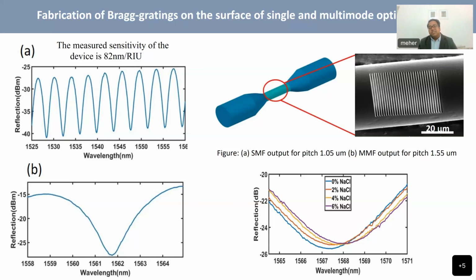These are really very challenging, and it took around a few months to optimize the process. Finally we could get it without coating any material. What people generally do, if they want to make surface patterns, is coat gold or some conducting material on the surface, and then make patterns, to discharge the accumulation of charges.